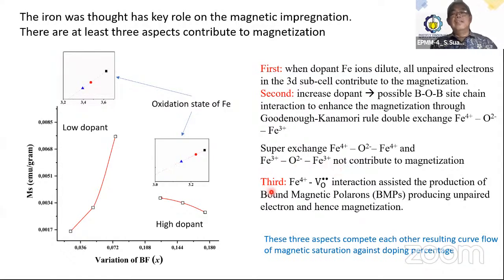The third, the interactions between the iron 4 plus and oxygen vacancy assisted the production of magnetic polarons producing unpaired electrons and hence the magnetizations. These three aspects compete with each other, resulting in a curve of magnetic saturations against doping percentage, in which it increases in the low dopants and decreases for high dopants.